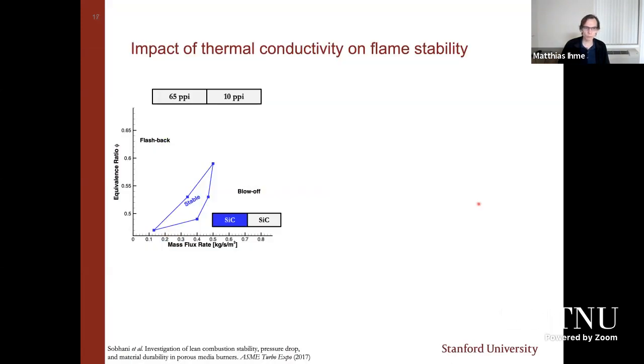Right. So the first diagram that I want to show you is a burner where we're using silicon carbide in both regions, in the flashback arrestor and in the combustion region. You're seeing typical stability limits illustrated by these lines here. These are measurements plotting the stability limit where we are retaining a flame as a function of equivalence ratio and the mass flow rate through the burner. And the system has a rather small region, simply because this is a silicon carbide system.